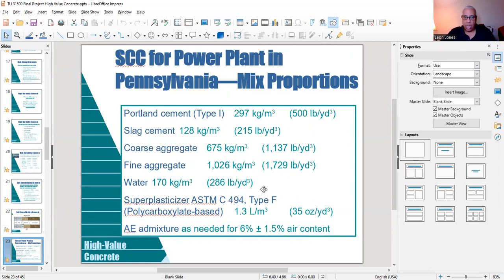And then you have your water. Let's put water in all concrete, 286 pounds per cubic yard. And you have your plasticizer. Now, again, plasticizer type F is based off of this specification, ASTM C494. And for your polycarboxylate base, it's 35 ounces per cubic yard. So your AE admixture as needed is 6% plus or minus 1.5% air content.